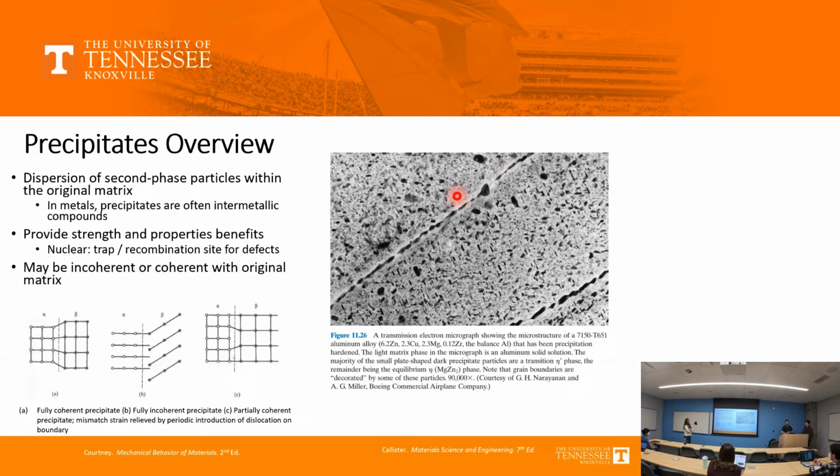And I will say, carbides are a very important type of second phase that are present in almost all metal alloys that are similar in some ways to precipitates, but distinct in others. I think generally they have higher melting points and form earlier in the processing. I would say also they tend to more heavily favor appearing on grain boundaries as opposed to within grains. But a lot of the techniques that we're going to discuss are also applicable to carbides in the sense that there are second phases that you want to get information about, and they often have similar property impacts or can have overlapping property impacts with intermetallic precipitates.